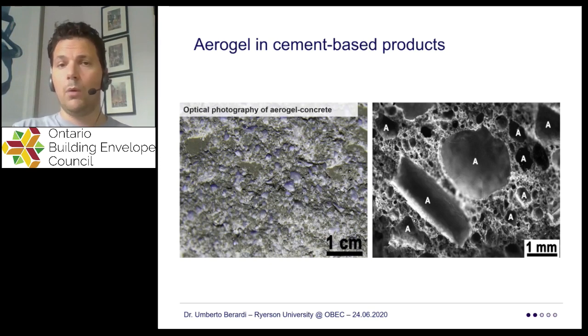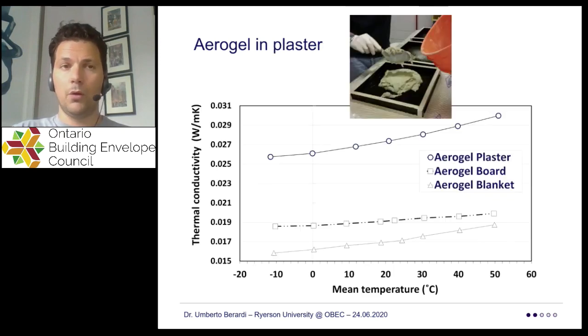And to be honest with you, we have already created concrete blocks with thermal conductivity in the range of 0.08. So with these mixes of aerogel and concrete we have already created blocks that are low in thermal conductivity. More importantly is the opportunity to use these days gypsum boards with aerogel, blankets with aerogel, or plasters with aerogel. These are all products that can be created with thermal conductivity below 0.02, so still values that are significantly lower than fiberglass. And they can be effective and useful in many different applications.